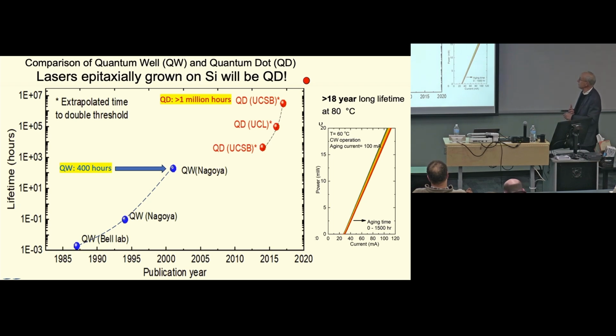It's because of the lattice mismatch, a lot of dislocations, the dislocations propagate, and the lifetime is terrible. With quantum dots, we're up to, at room temperature, 1 million hours. So 1 million versus 400 hours, there's a huge difference.